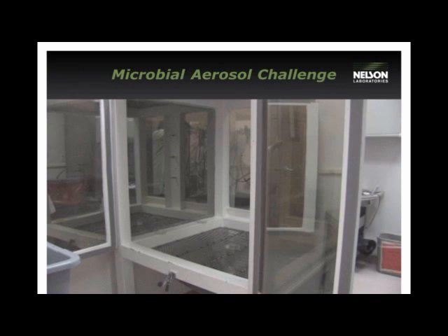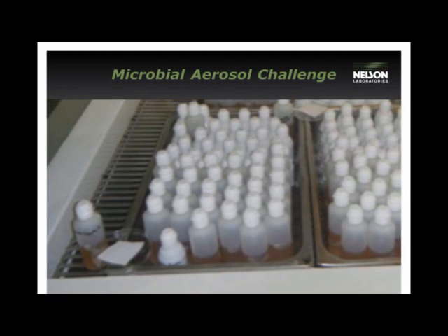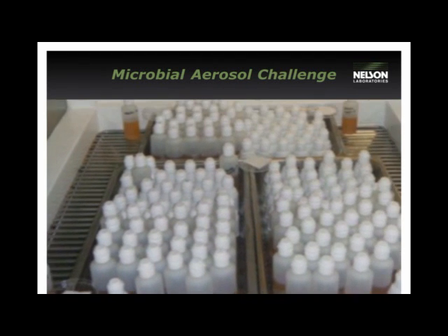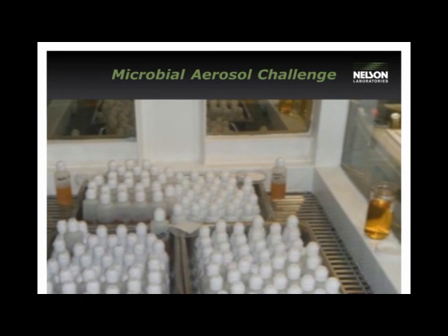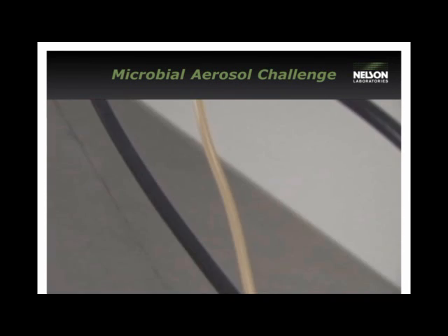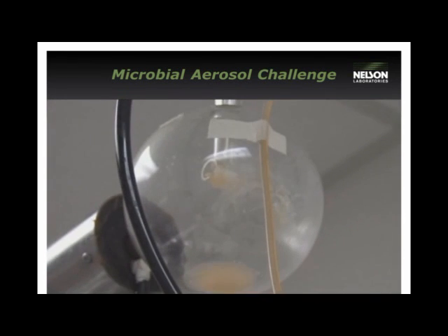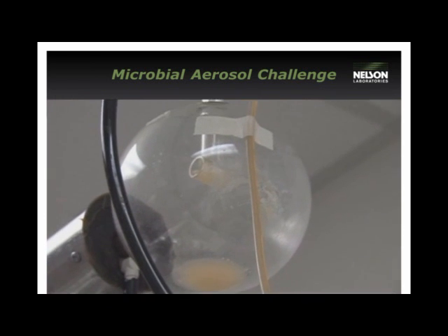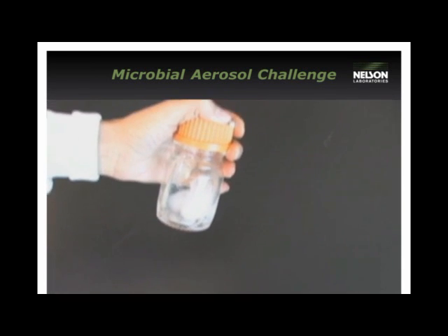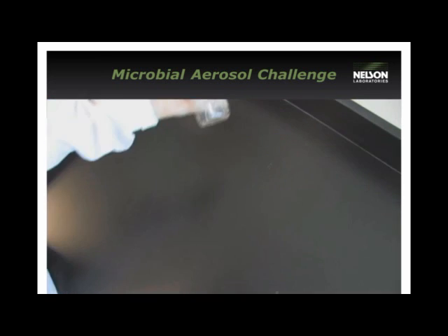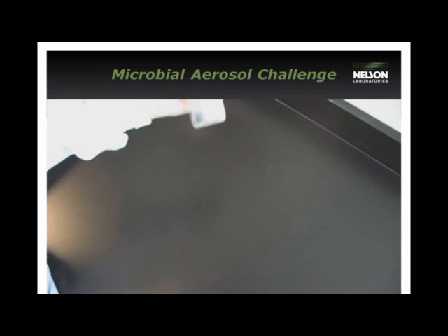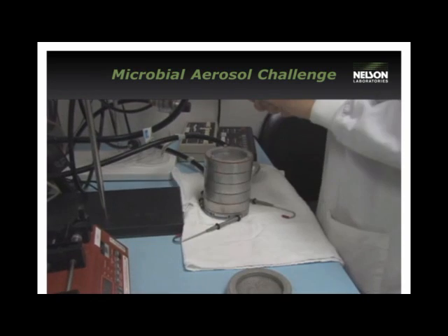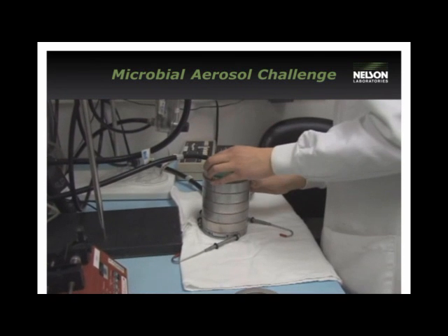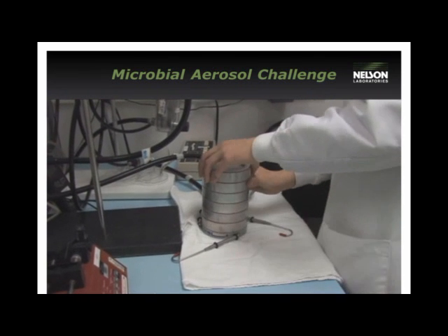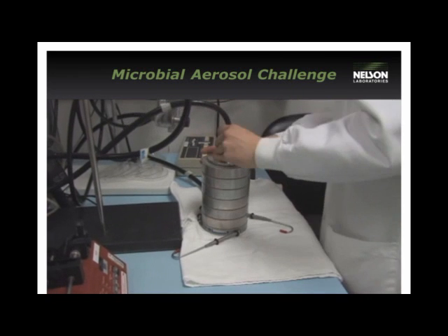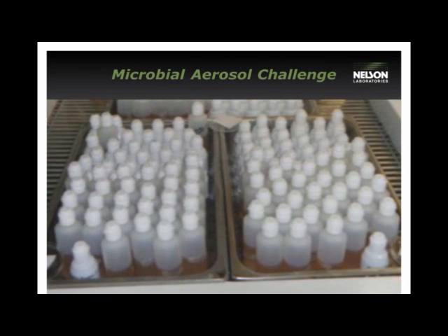Aerosol challenge is a microbial integrity test. Samples are loaded into a chamber, carefully spaced to expose as much surface area as possible, and showered with a vortex of aerosolized bacteria. Positive controls are run to ensure that the bacterial titer in the challenge met the specific minimum requirements. Andersen samplers are used to ensure the mean particle size is within a specified range.